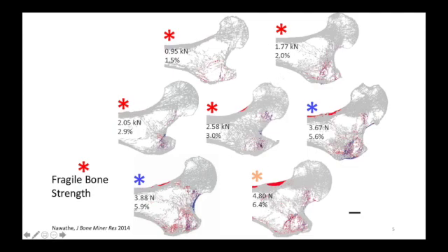And if you look at these pictures, what you can see is when you're at high risk of fracture, when the bone's about to fail, there's almost no failure of the cortical tissue. It's all in the trabecular bone. And on the bottom right, the strongest bone, you have to fail a lot of the cortical tissue. So the biomechanics are complicated in terms of how the bone is failing, cortical versus trabecular bone, and the relative importance of those.